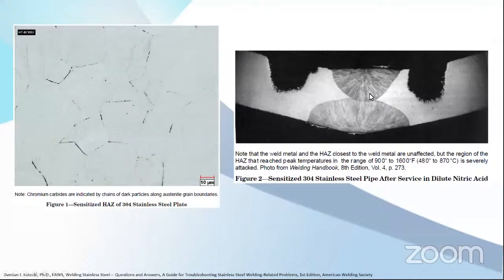This is when you have a macro structure. On the left is the micro. This is the macro. So you can see it happens in the heat affected area. The weldment itself, the fusion zone, is unaffected. It has very good corrosion resistance, but it affects the heat affected zones. It gets preferential corrosion because of the lack of chromium.